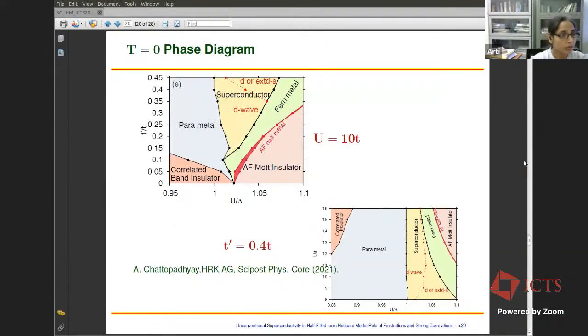So this is a complete zero temperature phase diagram, which I showed earlier also. So I'm just showing you different sections of the phase diagram. So now the electron-electron interaction has been fixed and I'm changing the strength of the second neighbor hopping. So you can see that for low values of the second neighbor hopping, the system does not have any superconducting phase. And once the second neighbor hopping becomes large enough, the superconductivity is induced by frustration of the magnetic order, and there is this parameter regime where both D wave and extended S wave superconducting phases are almost degenerate.